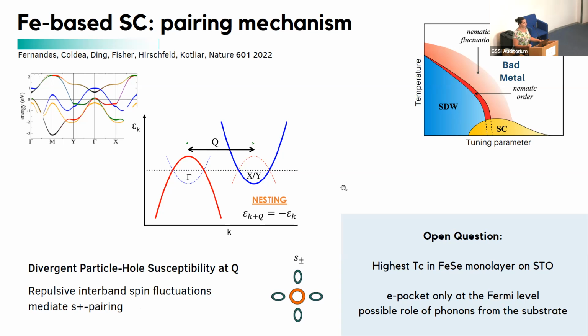In this respect, an extremely important open question is the iron selenium monolayer on strontium titanate, because this is the compound with the highest Tc, and it does not actually enter in this paradigm, because the hole pocket is pretty close to but below the Fermi level. So essentially a standard pure nesting mechanism would not work because you have only electron pockets. But I'm going to talk about that a bit later.